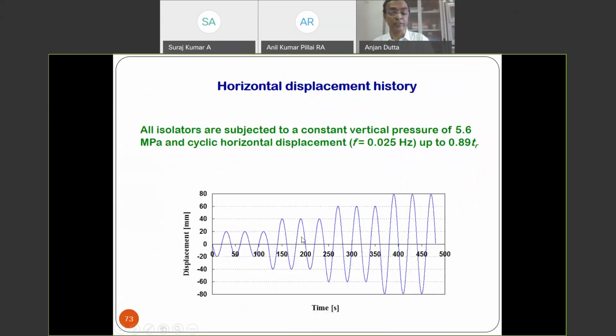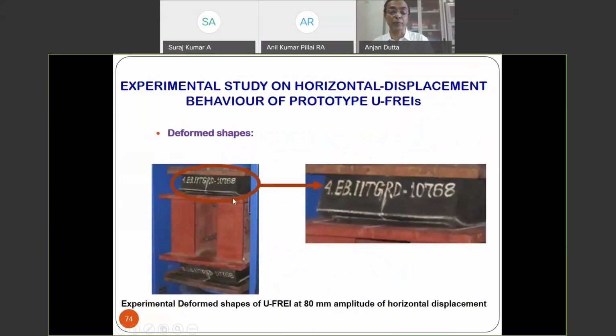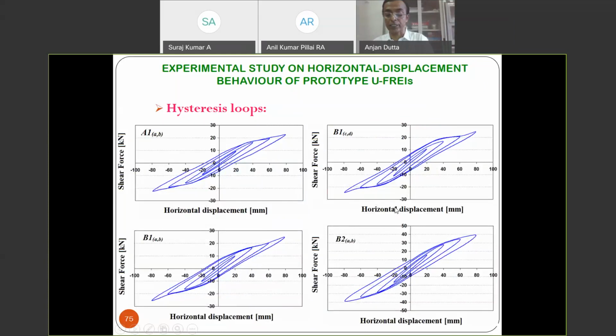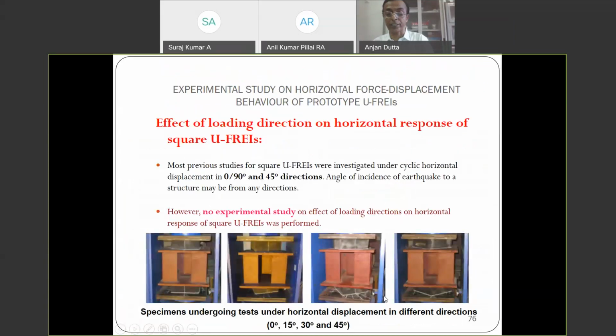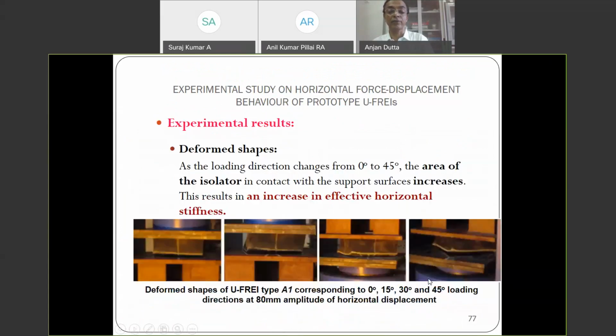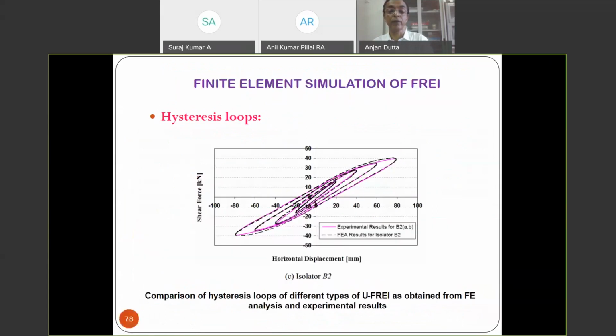Using this kind of setup, you can see this kind of rollover deformation. These are some of the static loops, and we have loaded them from different directions, starting from 0 degrees, because you do not know from which direction the earthquake will come. So you have to see their performance by loading them from different directions. We have loaded them from all possible directions, and you can see the corresponding rollover deformation for different directions of loading. And these are, again, the static loops when you compare the numerical one with the experimental one, and you can see a very good match.